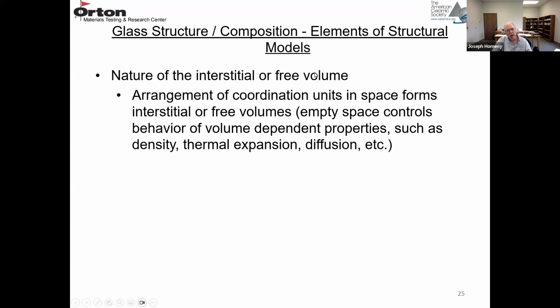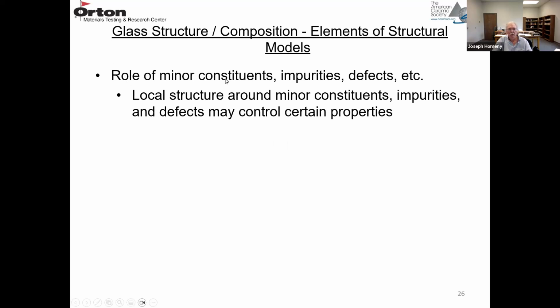And then the free volume in a glass, it has a more open structure than its crystalline component. Interstitial or free volume. When we look at the arrangement of the coordination units in space, they form interstitial or free volume. So there's an empty space in glass, and that has a big effect on the properties. It controls density, thermal expansion, diffusion. So glass has a lower density than a corresponding crystalline material, and those open spaces are important for determining glass properties. And then minor impurities, they're going to control certain glass properties. And when we look at the silicate glasses in a few minutes, we'll go over how the impurities affect the glass network and the properties.